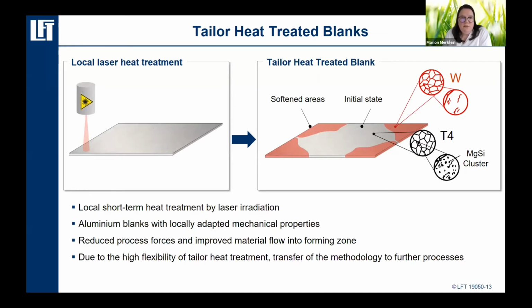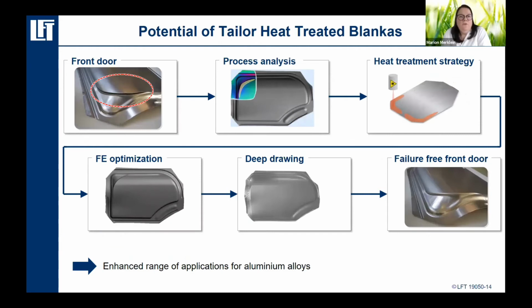The idea is to use a laser, for example, or any other heating device to have a very short local heat treatment, about 3-4 seconds, and to use the quenching effect and the solutioning effect of aluminum alloys so that we can soften the material locally. As a consequence, we can improve the material flow, we can lower the process forces, and we can flexibilize again the tools we use for different materials. In order to show this to you, I can give you here an example of a drawing tool that is used for drawing outer door panels. And this is designed for the drawing of a steel forming operation. And if you use an aluminum alloy, in this case a precipitation hardenable aluminum alloy, you can see at once that fracture may occur.